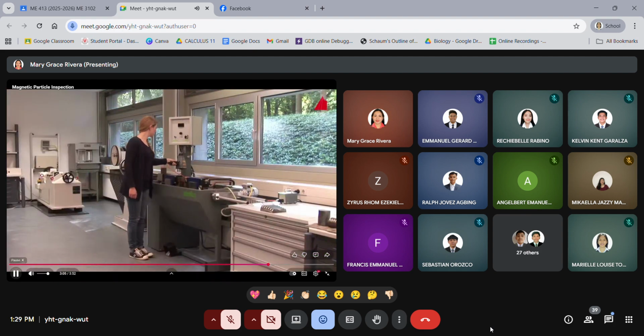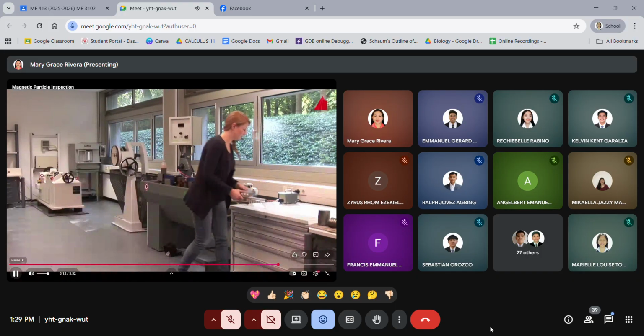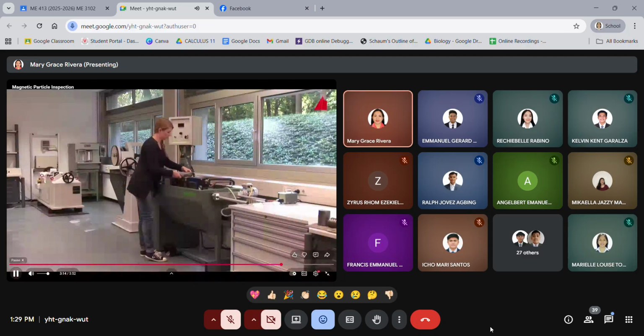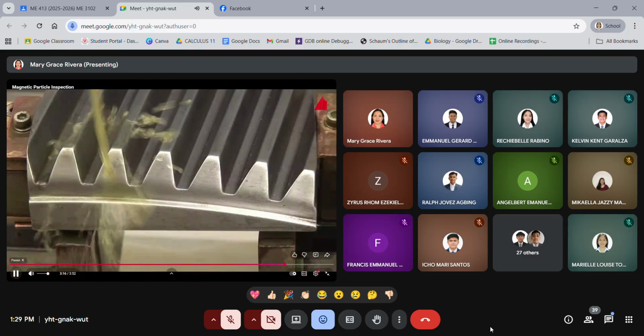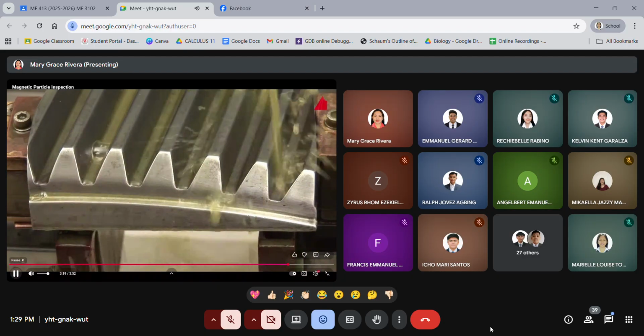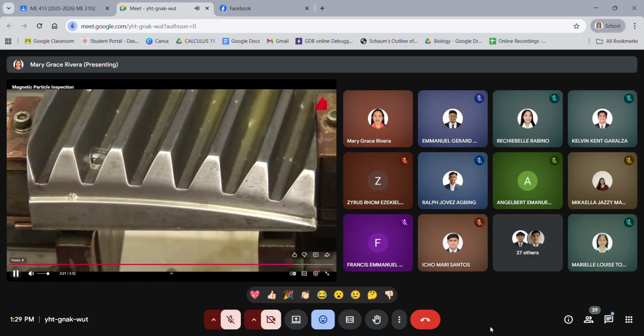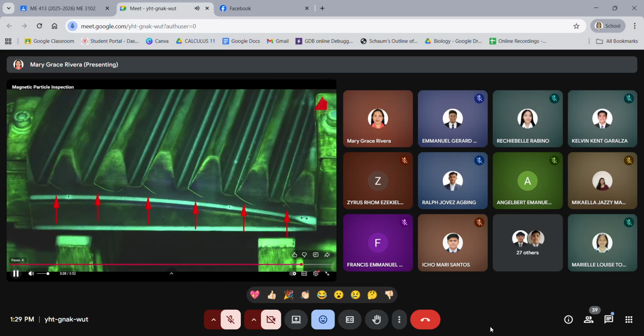Still another test piece has to face the magnetic particle inspection, a section of a large gear wheel. The same procedure again. Placing the gear wheel between the magnetic pole pieces, magnetizing and applying magnetic particle suspension. Already in daylight, there are indications of cracks, and again, they are best visible under ultraviolet light while darkening the daylight. The visible cracks are so-called fatigue cracks. They have been generated during the operation of the gear drive due to a mismatch of the gear wheels.